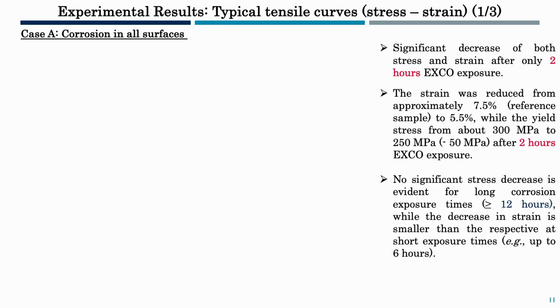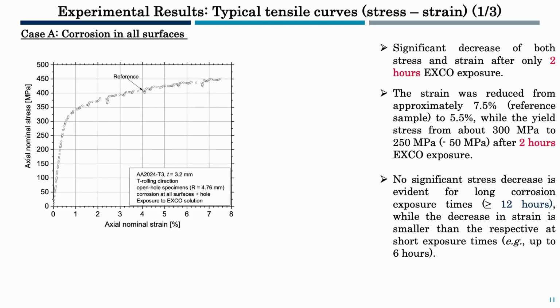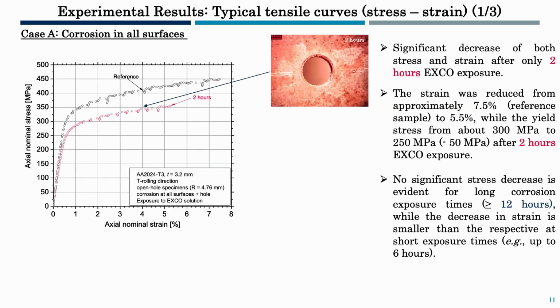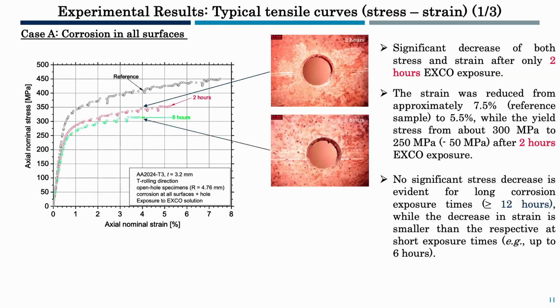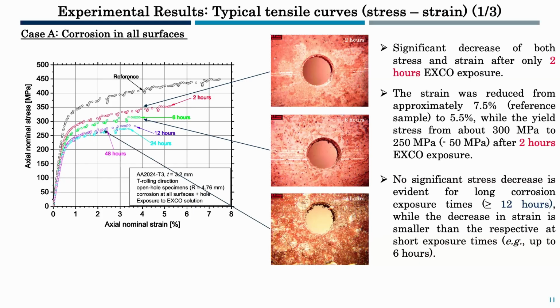Regarding the results of the tensile test, firstly, I'm going to show you the case A results for the corrosion in all surfaces. It was noticed that a significant decrease of both stress and strain is evident even after only 2 hours corrosion exposure time. And moving to higher exposure times, it is evident that no significant decrease in stress is noticed for the high exposure times, but a significant decrease in strain was noticed.